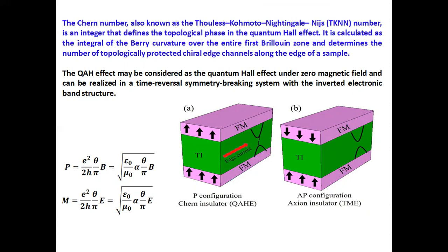The moment you are not convinced of your doping method, you cannot clearly generate a band gap sufficient to prevent its topology from collapsing at a high enough temperature. Are you getting my point? Because it already has a conducting surface state, that conducting surface state has to interact very strongly with your magnetic dopant. Then only will a very big gap open, and then only can you have a proportionately high enough temperature. So you are saying that unless the dopant distributes itself uniformly, you cannot have a magnetic topological insulator with a high sustainability temperature. Right. This is one problem.